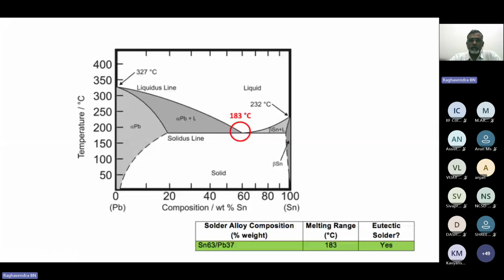And for making an alloy for soldering, we need tin and lead material. If anybody is manufacturing this solder alloy, definitely the lowest temperature will be ideal for this application. Through the phase diagram, we came to know that the lowest temperature is 183 degrees, and for achieving the 183 degree melting point, the composition should be 63% tin and 37% lead. So this we come to know by understanding the phase diagram.